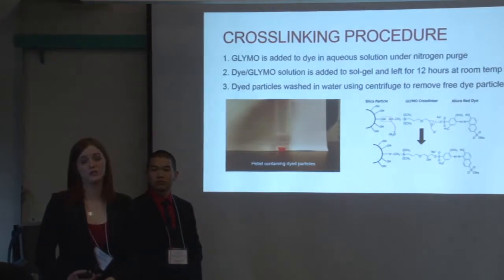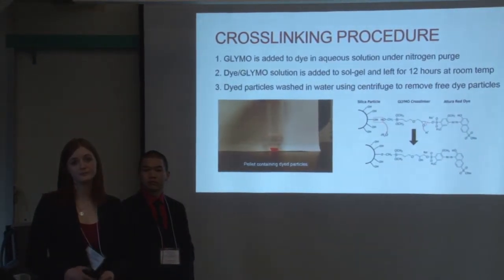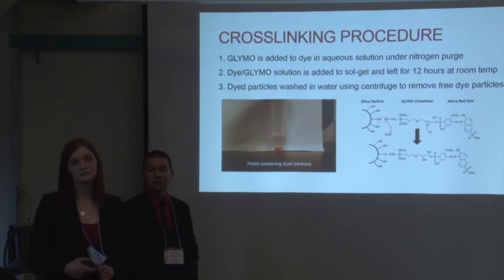It's difficult to get 100% yield. And also to control... Did you do this in 2 steps or in 1 step? In 2 steps. Well, you mean the synthesis process? Yeah. The synthesis is a 2-step process, but we mix the crosslinker with the dye first, and then we add that to the sol gel. Because that epoxide group can react with other things as well.